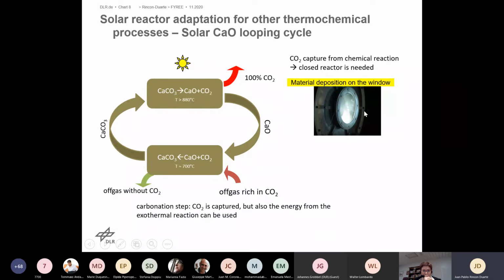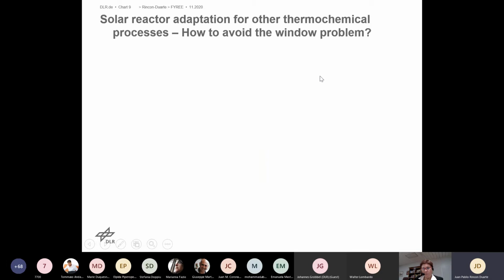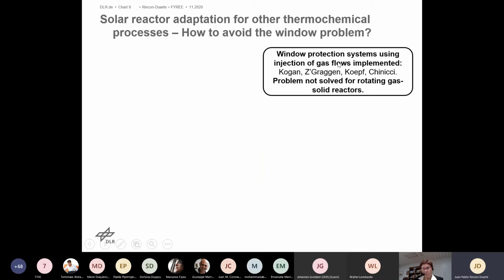But here we are talking about different material conditions because the particle sizes are in the range of microns. We observed in one experimental campaign that the finest particles tend to migrate to the window. After some minutes, the window is covered by particles so that the solar radiation cannot enter anymore inside the reactor, and the window is overheated and it breaks.